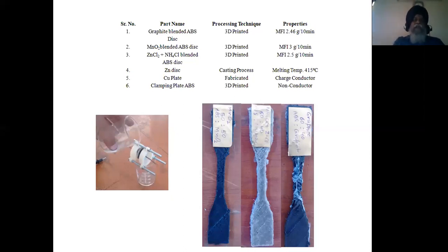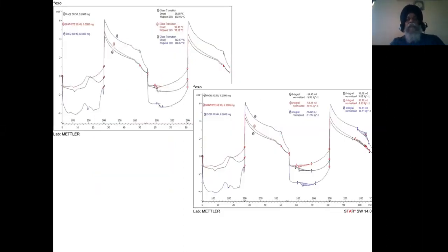Now you see, if the whole assembly is in the form of discs, and one particular disc is consumed because of the transfer of the electrons or the flow of the charge, as a typical mechanical engineer, I can just open it and assemble that particular disc, and my assembly is supposed to give me again a similar voltage. Again, from the typical mechanical engineering point of view, we measured their mechanical properties using standard tensile and compressive specimens. Now this is really important.